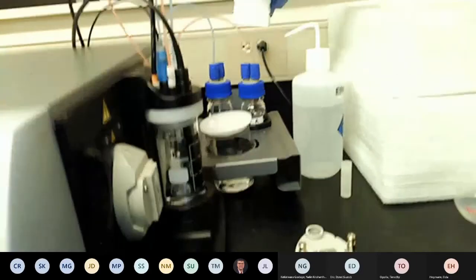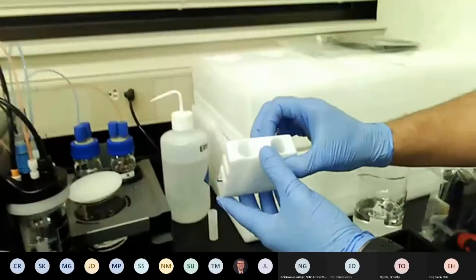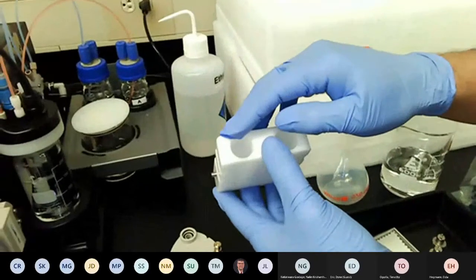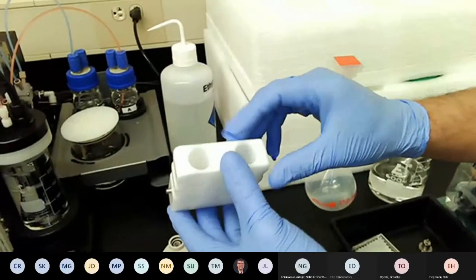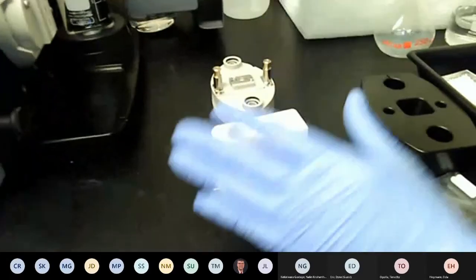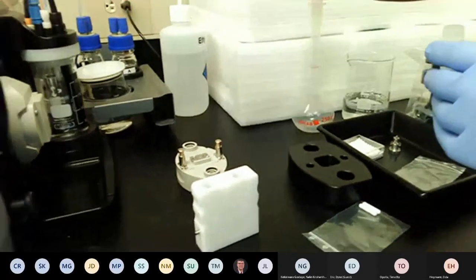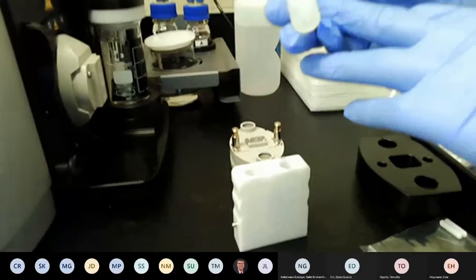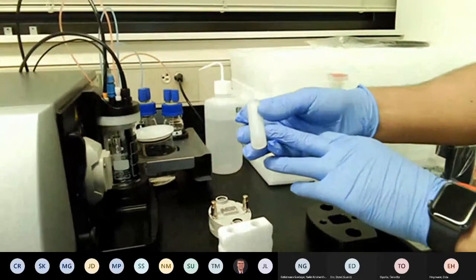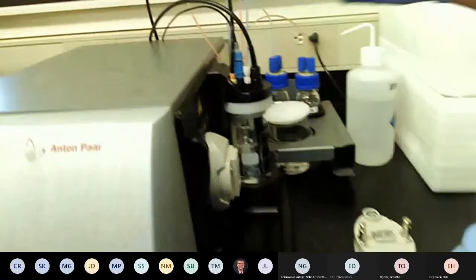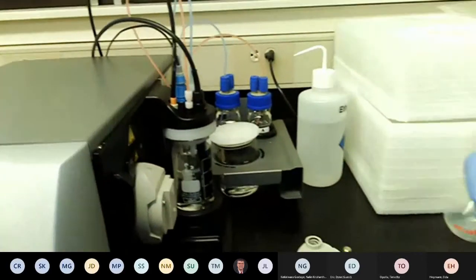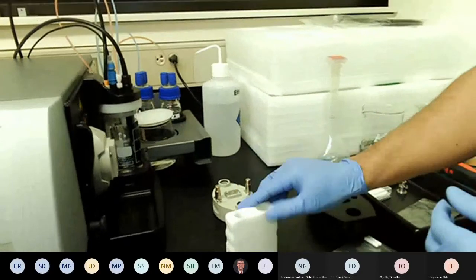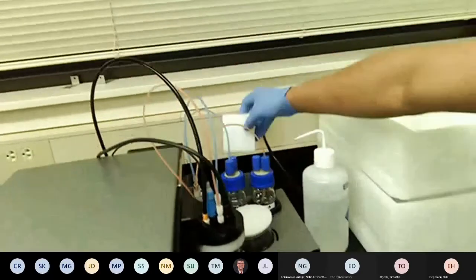And then lastly, when you're not using the instrument, you have this part which can hold the conductivity probe and the pH probe. It's very important, for the pH probe specifically, that this will be generally filled with a little bit of 3 molar KCl to make sure that the pH probe is sitting in that. Otherwise, you don't want it to dry out. And then this just goes over here.